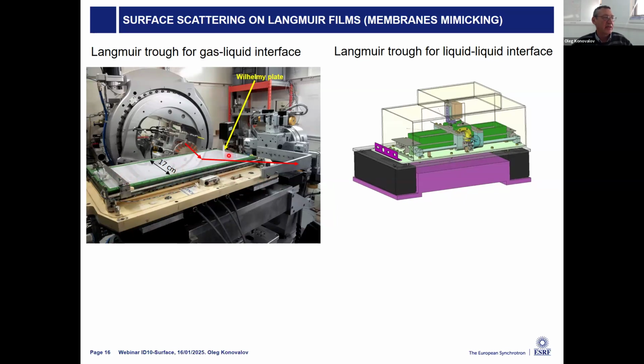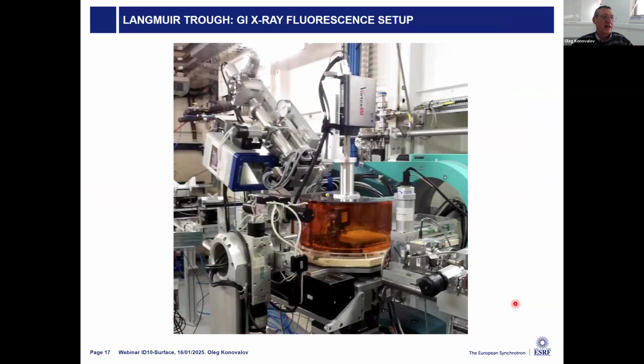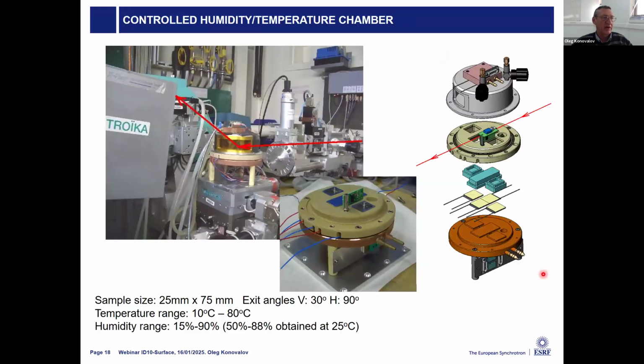area. In this direction it is about 0.5 meter, and the beam goes to this liquid surface, and then we do all the measurements. Or we also have a special Langmuir trough to work at a liquid-liquid interface. So this is a Langmuir trough for that. This is an example of the setup where we measure at the same time on a Langmuir trough with 3 detectors: reflectivity, diffraction, GID or GISAXS, and also the fluorescence detector. So we get 3 types of information from the same sample.